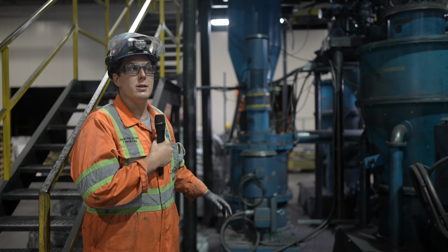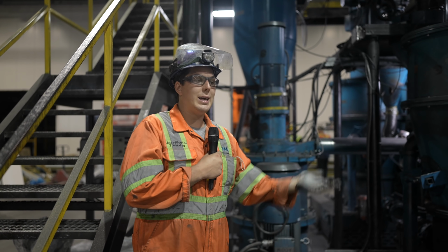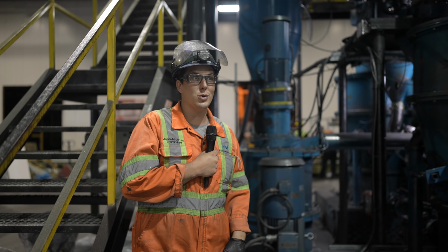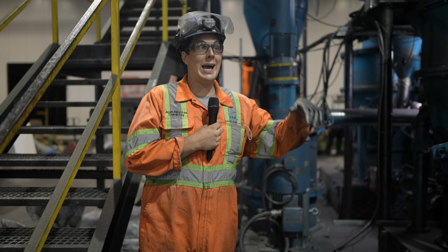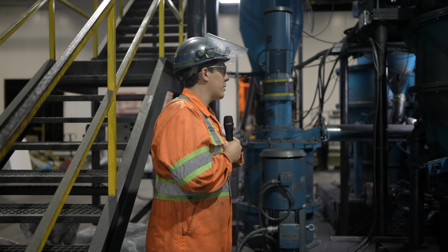So this motor is like a turn hammer that breaks the particles into very small ones, and this motor is a classification wheel. It's a wheel that turns inside, and there's an air stream that lifts the small flakes, and if they're too coarse, like 50 microns, they're going to get hit by a paddle of the classification wheel because the speed is too low. So they get back onto the hammer, and when they are the good particle size, they get passed through the wheel, and the airstream gets them to the big bin that is up here.